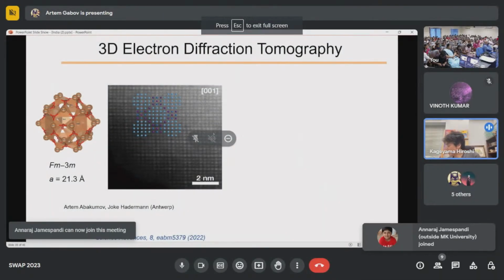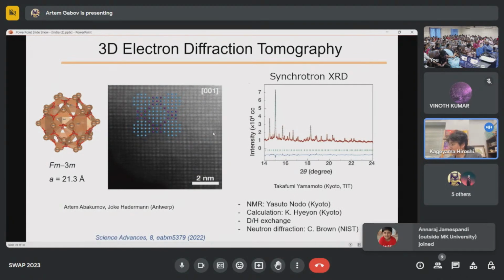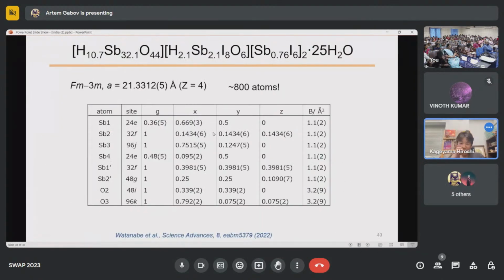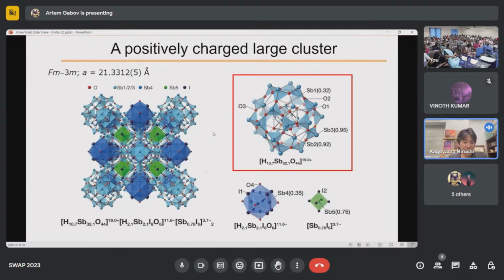Then we finally solved the crystal structure. And in fact, this material has more than 800 atoms in the unit cell, which is completely different from our expected crystal structure. So this is not a topochemical reaction, but some unexpected serendipitous discovery. Okay. Then this is the crystal structure of the final material. This light blue is showing the positively charged large clusters forming the FCC unit cell.